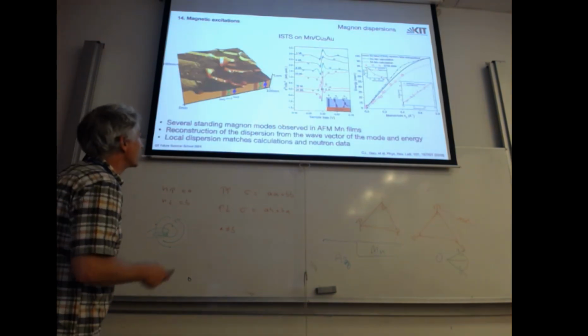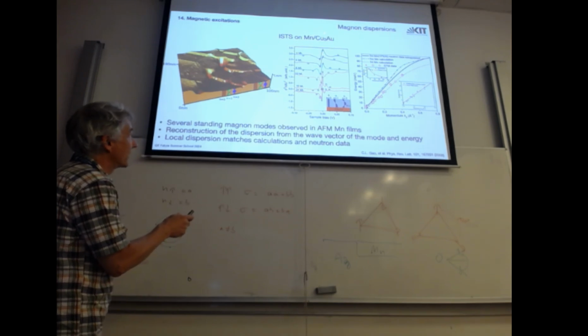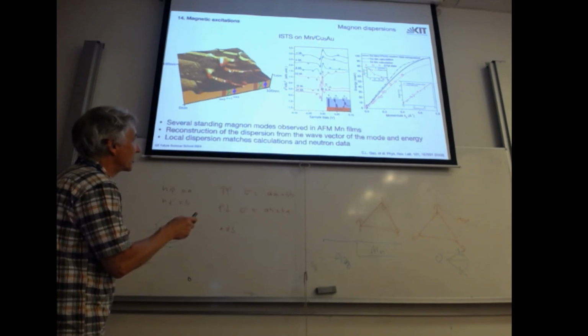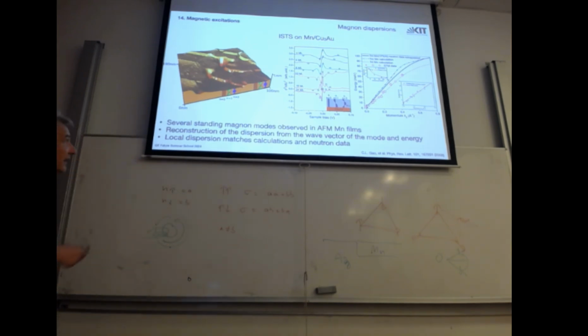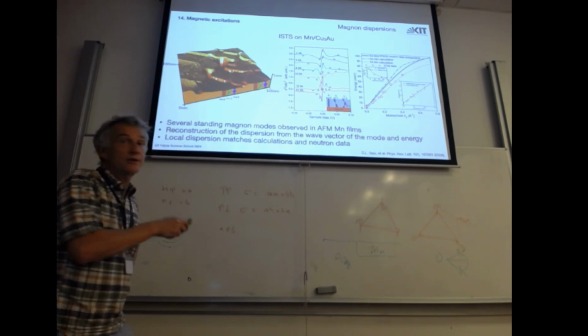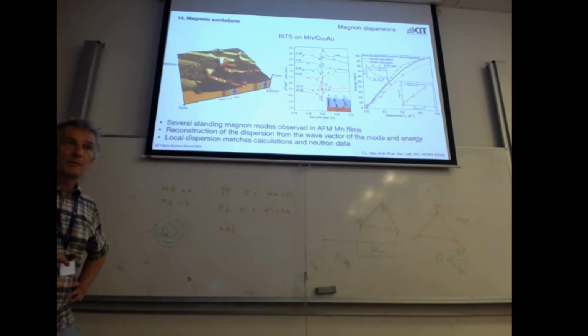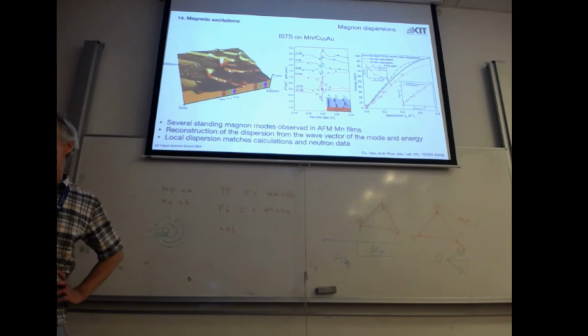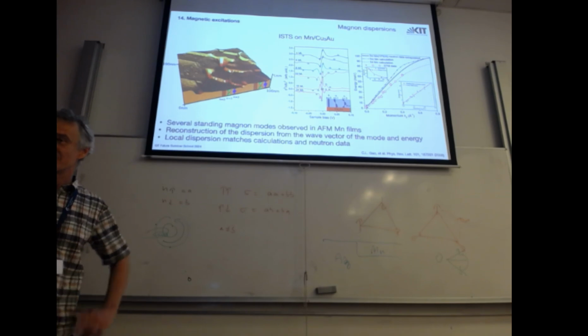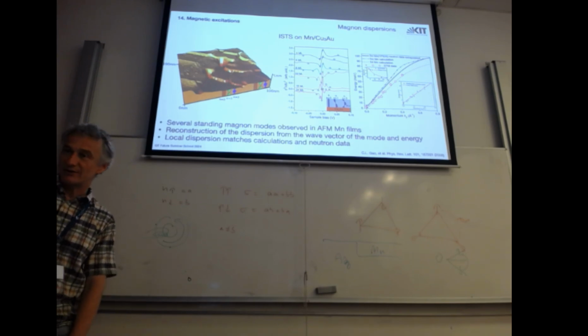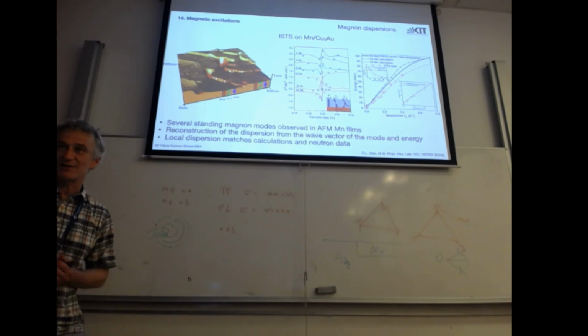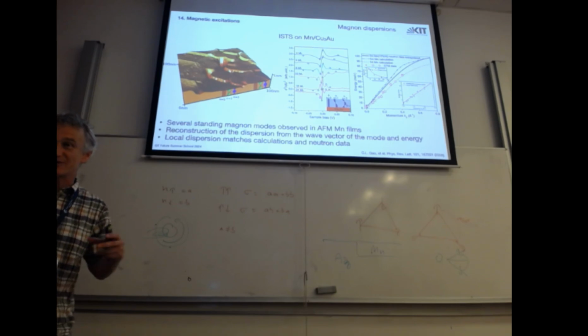So the easiest way to do it is to go again to an antiferromagnet. Manganese on top of Cu2Au. This is again a layer-wise antiferromagnet. We have different thicknesses here. And these are the differential conductivity plots now. In an antiferromagnet, we have the same number of minority and majority electrons. So all of the bands are spin degenerate, but fully spin polarized. Yeah, you have an up band and a down band on top of each other, but they live on different atoms.